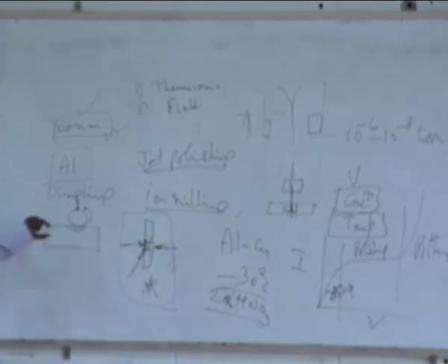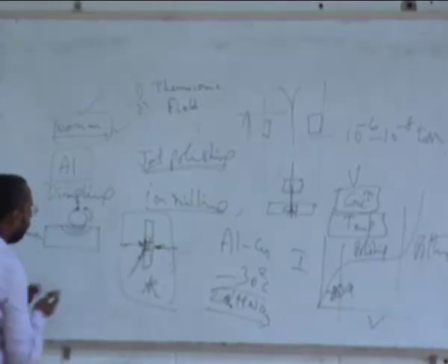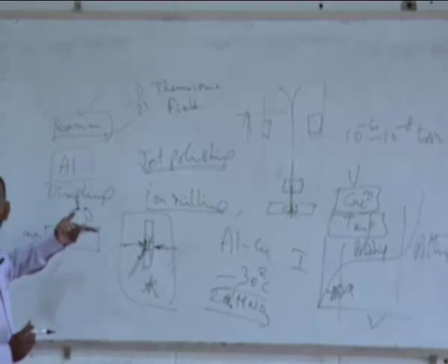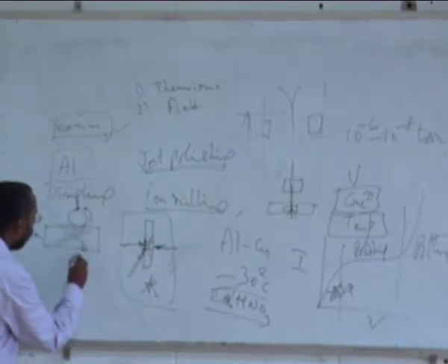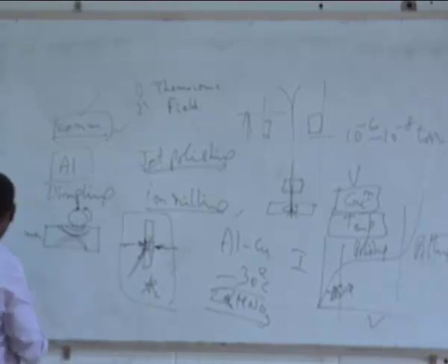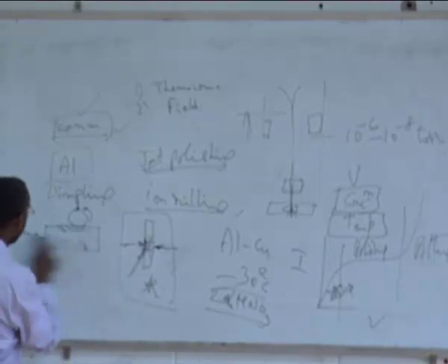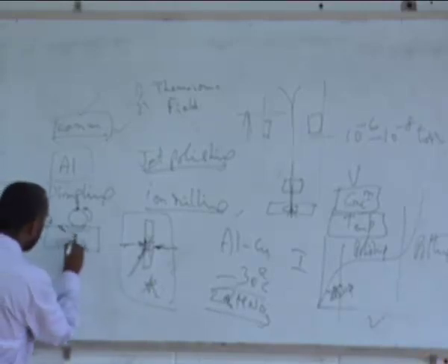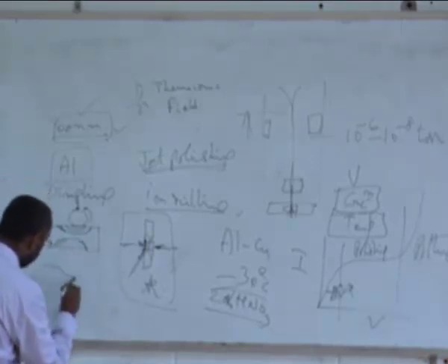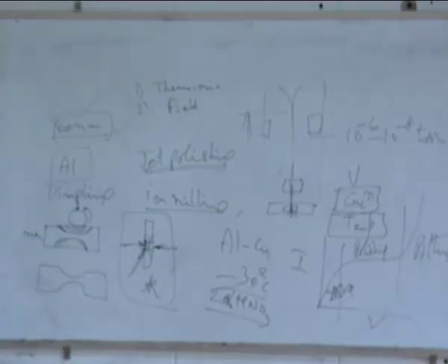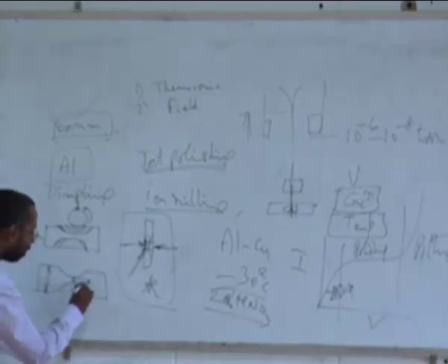And after it forms a certain dent, if I invert the sample and do it again on the second side, you will see on the other side also you will form a dent. So you are not interested here in making the hole, but simply in reducing the thickness like this, so that now your sample is something like this. So from 100 microns, you have brought it down to around 10 microns.